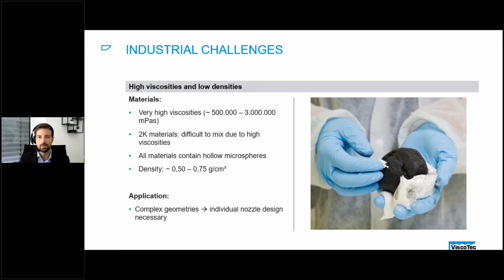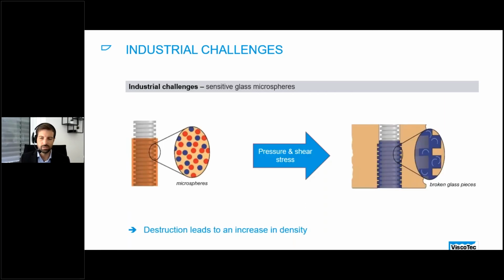So next slide, please. In comparison to the sealant applications, we have here glass microspheres, not polymeric microspheres, and this is a huge difference because the glass microspheres are pressure sensitive and can be destroyed by high shear stress. Again, here our technology is a perfect match because we have a low pressure system and a low shear system. So we don't put much shear stress on the material itself. This fact requires extremely gentle handling, as they otherwise would be destroyed, which would result in an increase in density.